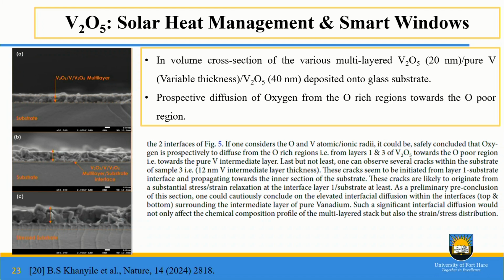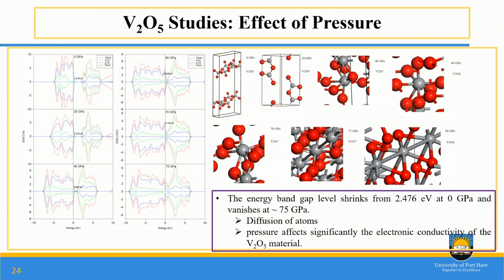This is the work that we have done for Itemba Labs. This is the experimental work, and this one is our computational work. They wanted us to check if there is any diffusion of oxygen on V2O5, and we have seen that indeed at 0 GPa you have V2O5, and when you go further, you get more bonds compared to what you have initially. So we concluded for them that yes, oxygen does diffuse as you increase the pressure.